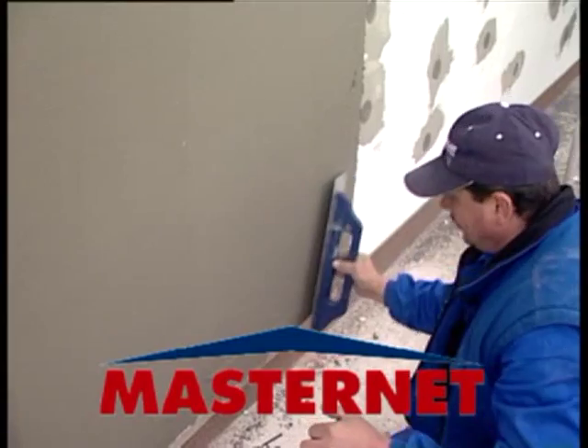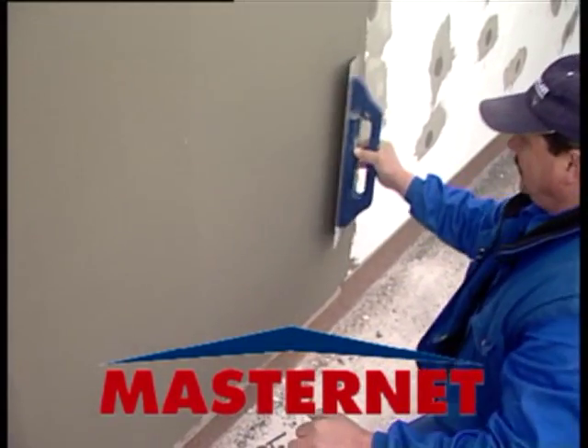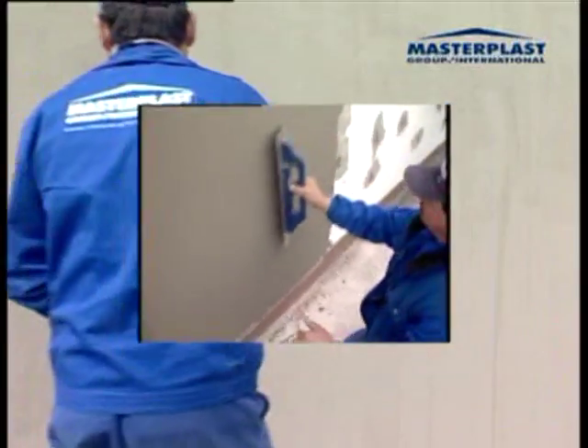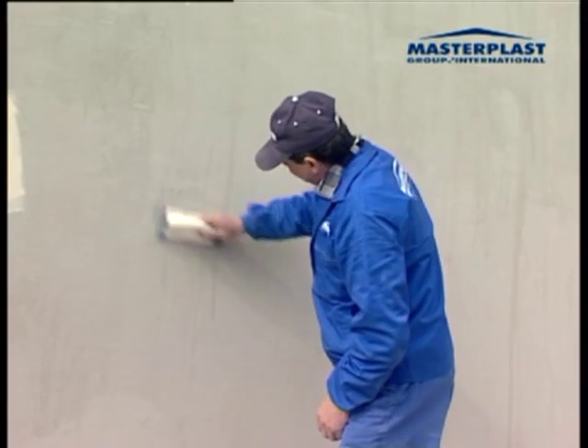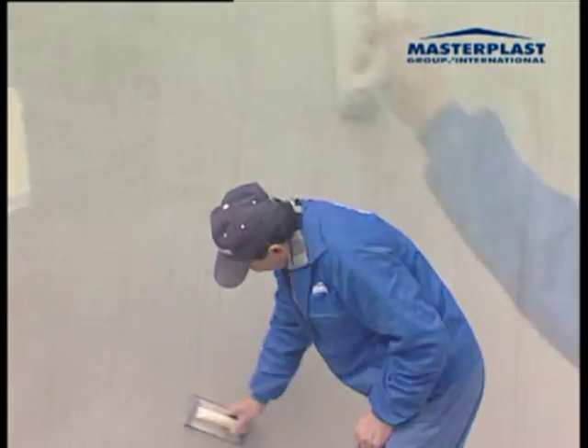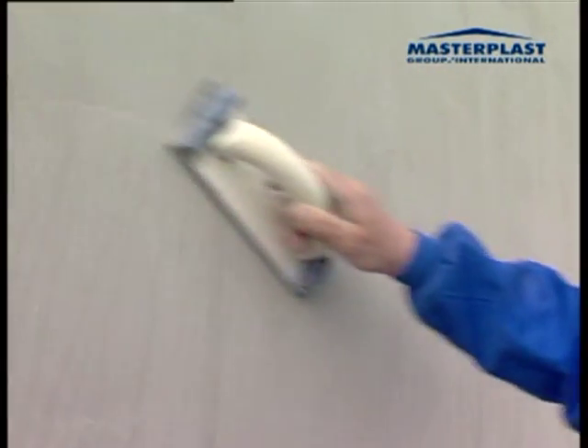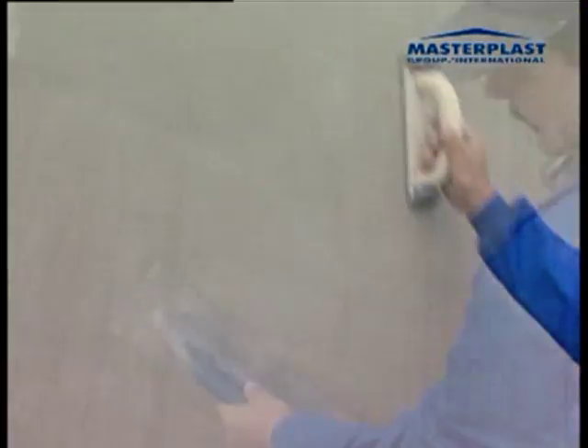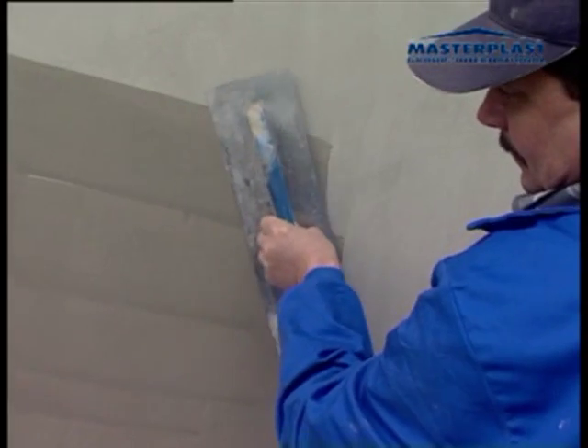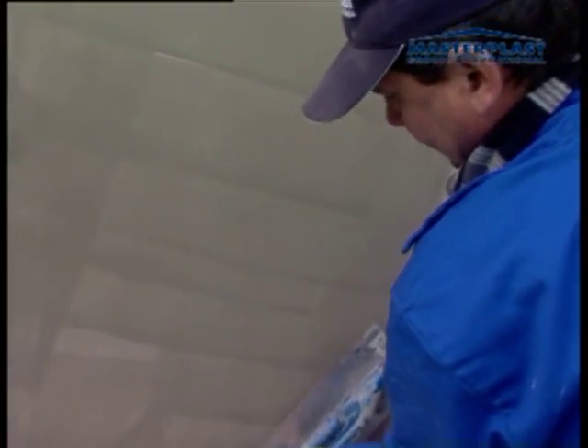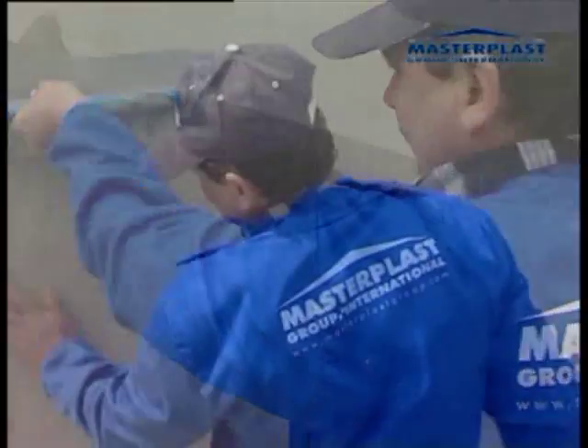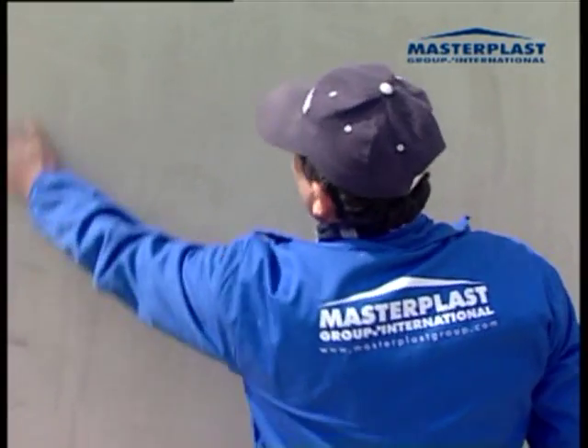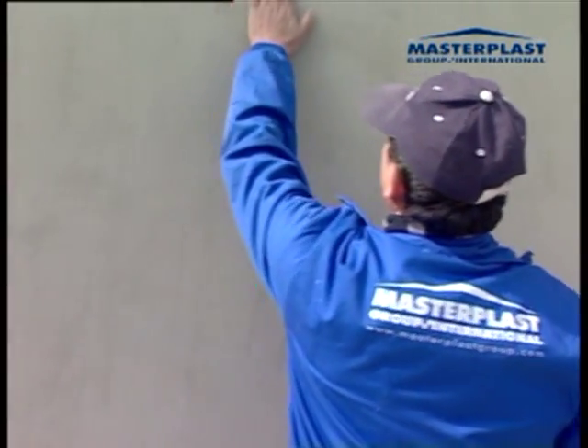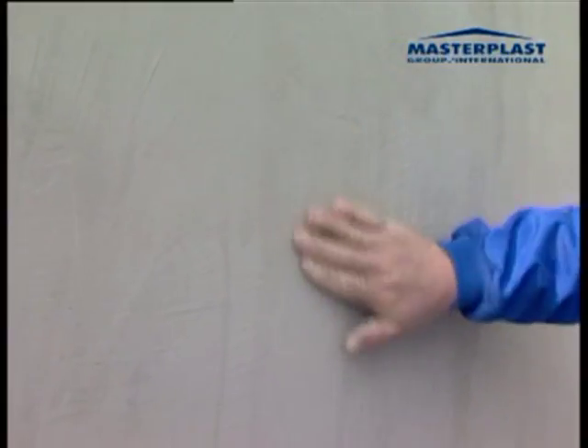The fiberglass mesh is not visible if the base coat was done properly. The surface is even and smooth. If needed, after the bonding of the base coat but before the complete hardening, 1 to 3 days after the work, grind again with an emery and apply a thin layer of plaster with a plastering trowel. It is worth checking the surface with a surface side light, and if needed, you should carry out the potential reparations before putting on the expensive final cover layer.